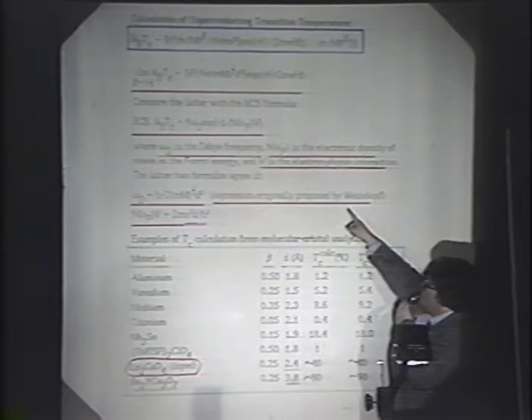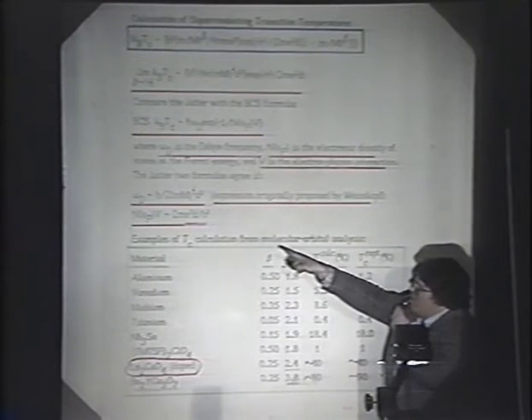This particular formula reduces to the BCS type formulas in the case of beta being a half, if the Debye frequency can be expressed in this manner, an expression originally proposed by Weisskopf, and if the density of states times the attractive potential can be expressed in that way.